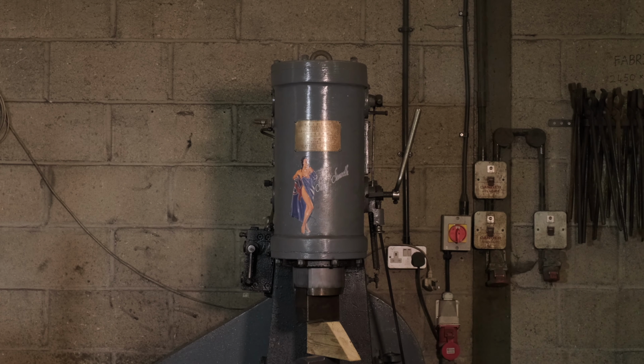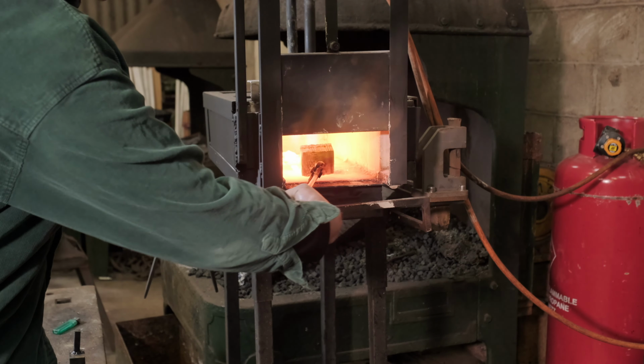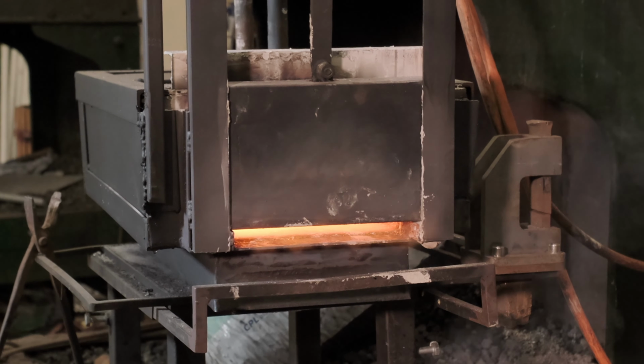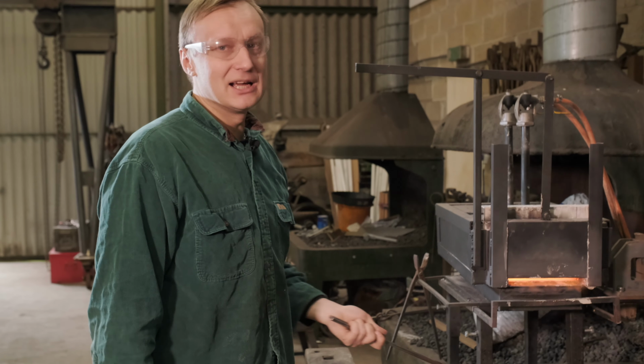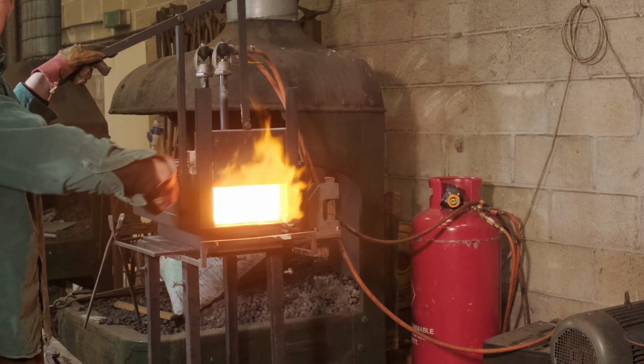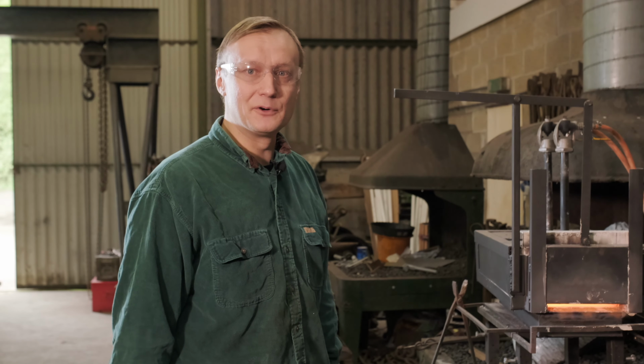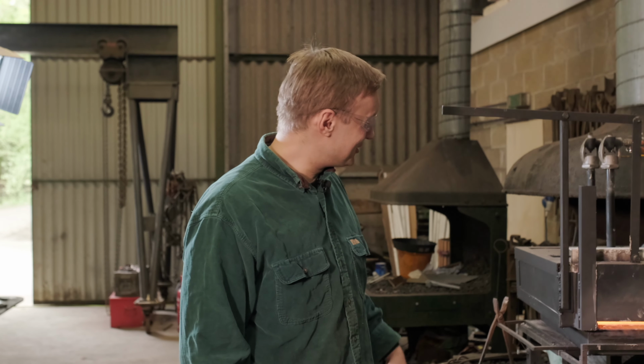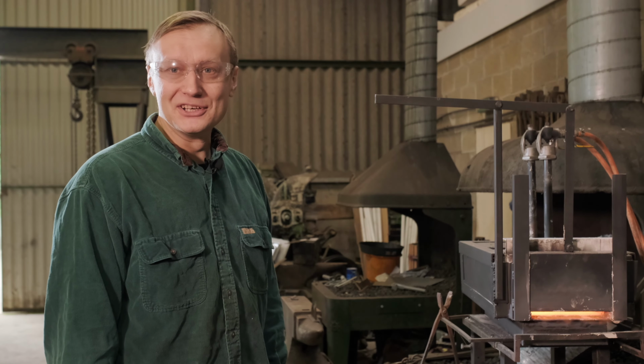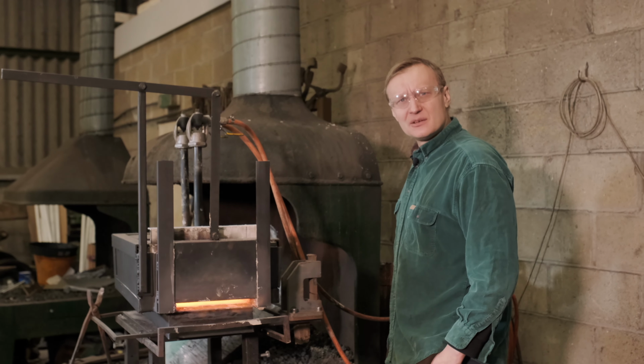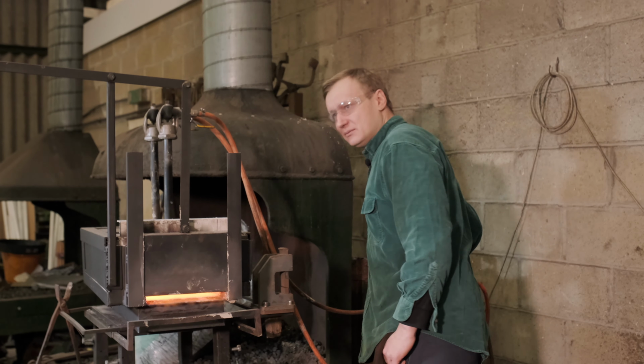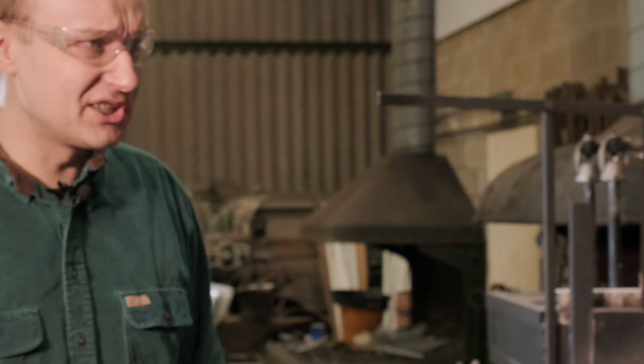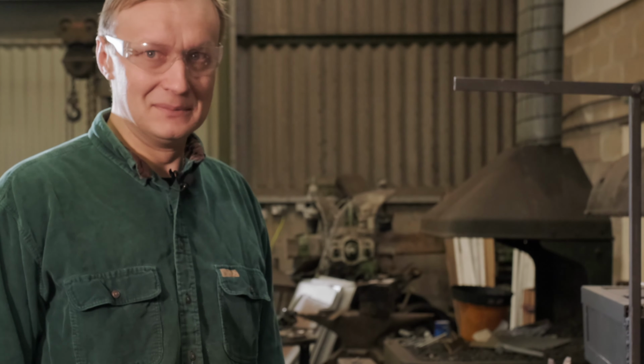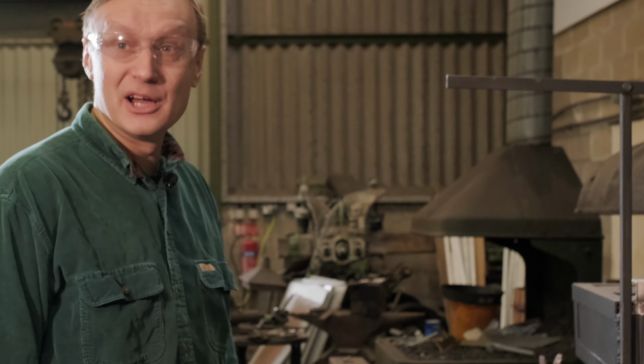So at the moment you see that it starts to pick up. It's been there for like a minute or two, so there's barely any color in. But what I'm gonna wait for is for the stack to get nice and yellow, pretty much the same color as the inside of the forge. That's a good indicator for the temperature. If you want to go fancy, you can get a thermocouple and just drill a hole in the forge and get yourself a proper measurement. But I can't be bothered. 100 quid, something like that for it. It's not like super expensive, but they do get messed up fairly quickly. At least the one I bought a couple of years back, it got melted pretty much straight away after a couple of uses. Maybe I used it wrong, I'm not really sure.